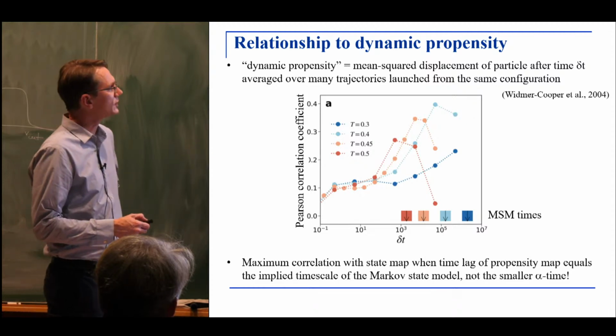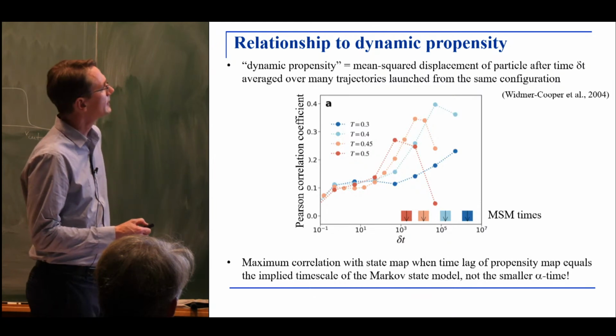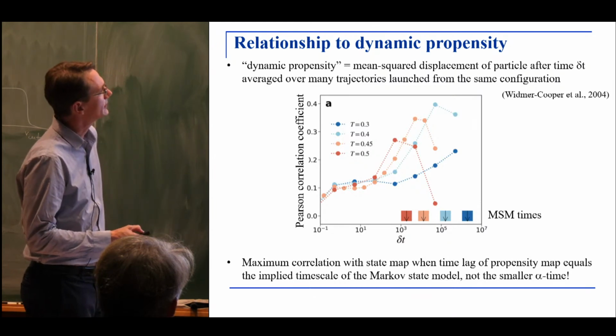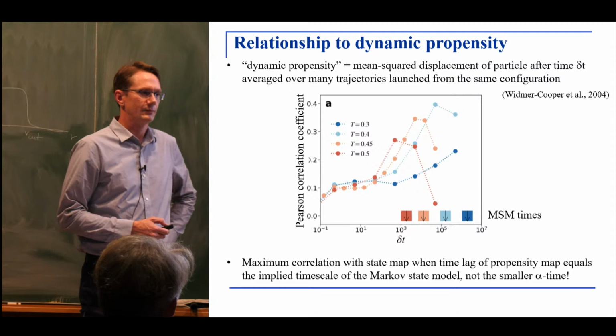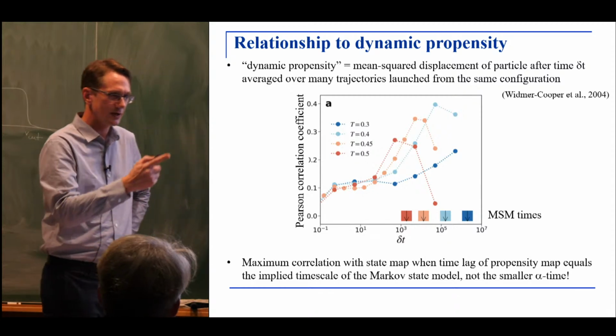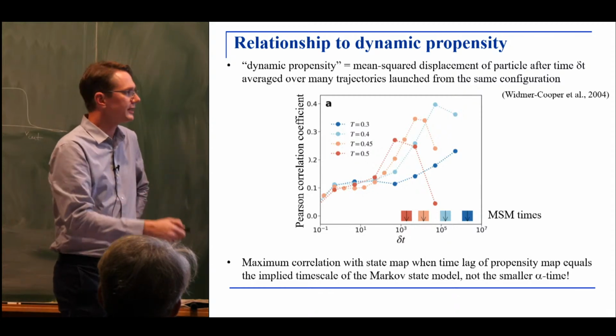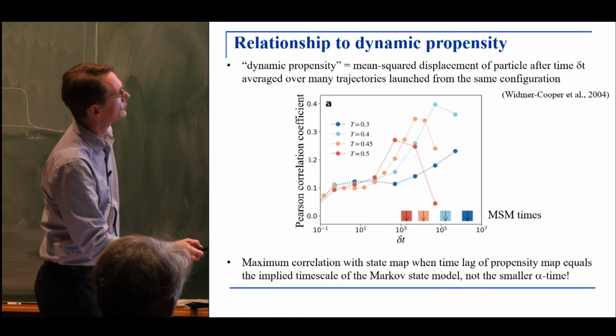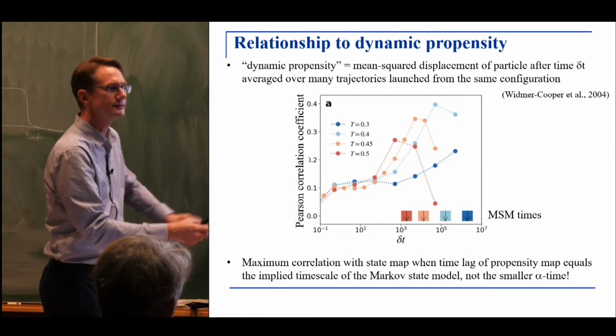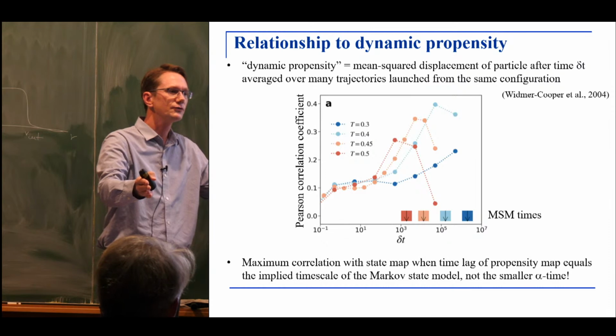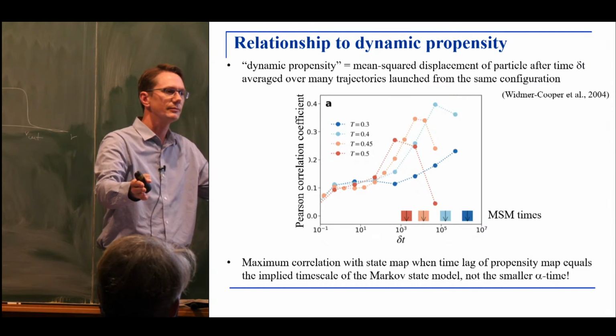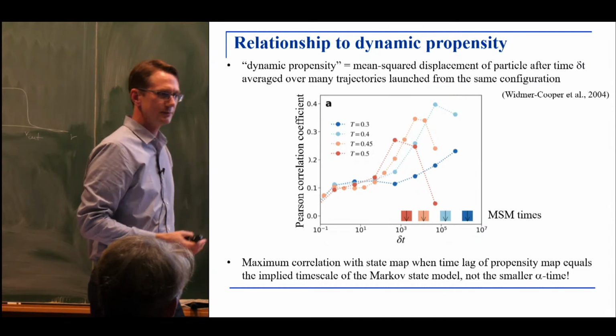And what I want to point out to you is, however, that this maximum occurs not at the alpha time, which is what was found in studies like yours and others, but at a much later time, which corresponds to this Markov state model time. And that is the decorrelation time of the Voronoi volume map. And Daniele seems to disagree, or?